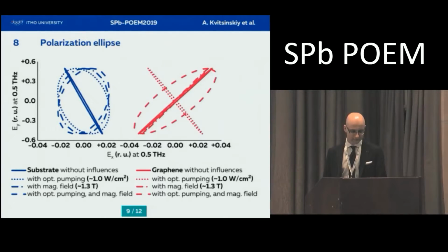The changes in angles of the polarization ellipse might be connected with the Faraday rotation effect. Applying a magnetic field to an isotropic material causes anisotropy, and as a result, circular birefringence. Taking this into account, the vector of the transmitted linearly polarized wave is not the same as it was before the sample. So polarization angle rotation caused by the Faraday effect depends on free carrier concentration, which can be increased by optical pumping, and the value of the applied magnetic field.